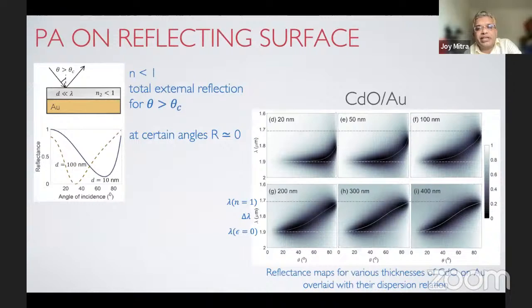Yes. Well, the cadmium oxide is very different. We chose cadmium oxide simply because it has a much lower epsilon double prime. Actually, the number density is also low because the lambda ENZ is more redshifted. But the primary advantage of these materials is how far we can tune not only the epsilon prime, but the epsilon double prime, which is the loss in the system. No, the number density is not a very strong function, at least within the range. But that's your tuning with the oxygen vacancies, right? So if that would change with thickness, right? Well, that's what I'm about to say.